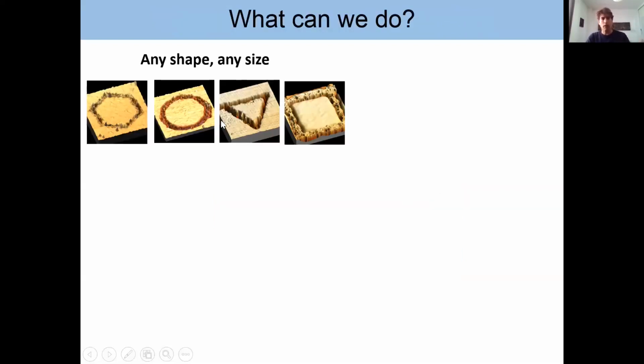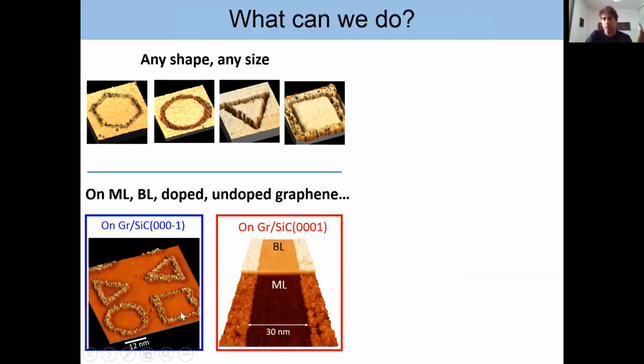So as I told you, we can do essentially any shape, but also any size. We can do very small ones, a very few nanometers, and we can go to hundreds of nanometers. We can go even to microns. We are just limited by the scanning range of our microscope. It appears to work in all graphene samples where graphene is decoupled. We have tried on the carbon face, on the silicon face, on multilayer, on monolayer, on bilayer. Apparently, in any decoupled system, it works.